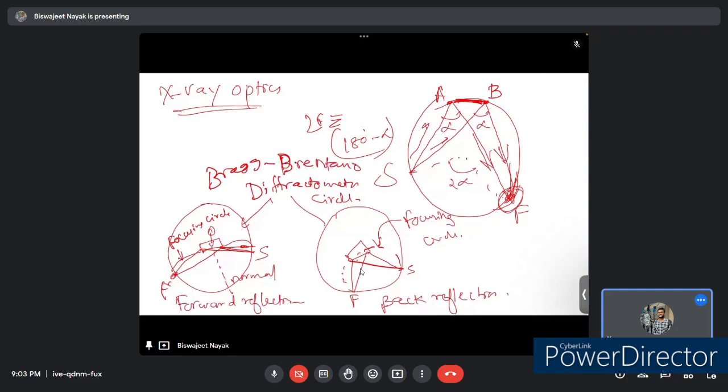For any position of the detector receiving slit F, the X-ray source S is always located on the diffractometer circle, which means that the face of the specimen, because of its mechanical coupling with the detector, is always tangent to a focusing circle centered on the normal to the specimen and passing through F and S. The focusing circle is not of constant size but increases in radius as the angle 2 theta decreases.